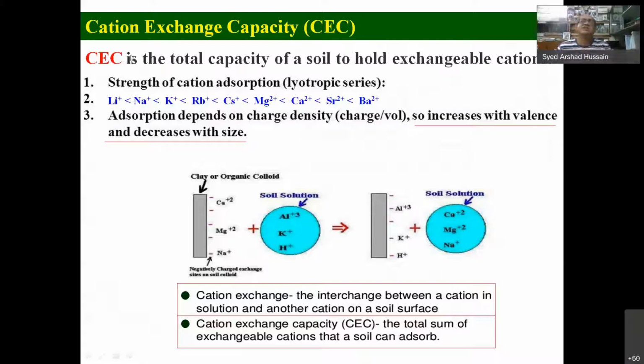Another thing is cation exchange capacity. This is very important. Cation exchange capacity is the interchange between cations in the solution and the cations within the clay surface. In this way one can incorporate other material having different cations attached with this material in the system through cation exchange reactions, and it's measured. The extent of capacity of this exchange is measured in terms of CEC, cation exchange capacity, and this is the total capacity of a soil to hold exchangeable cations.